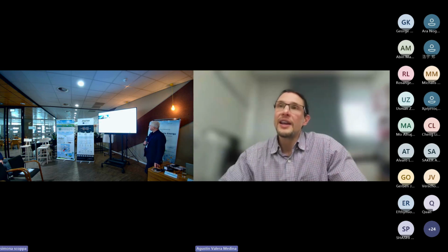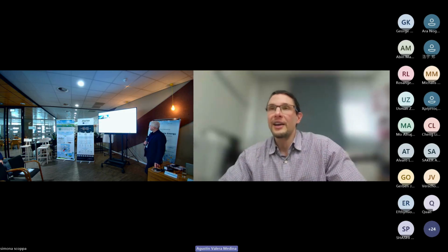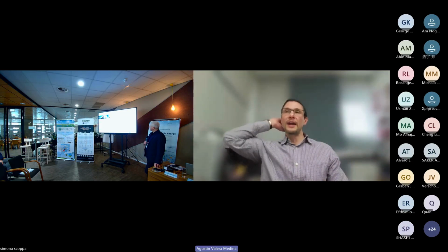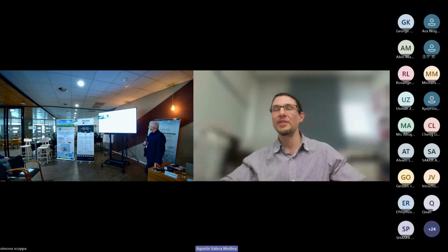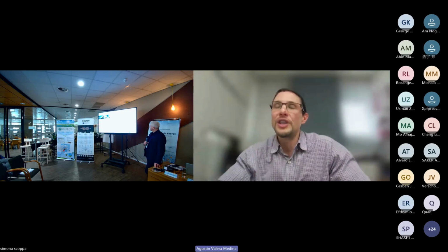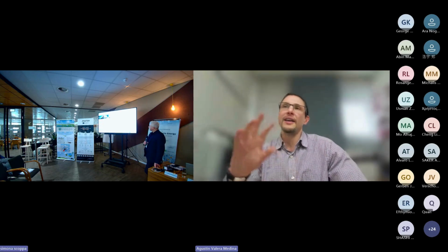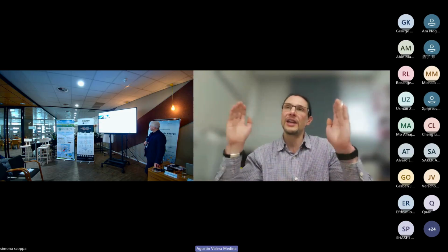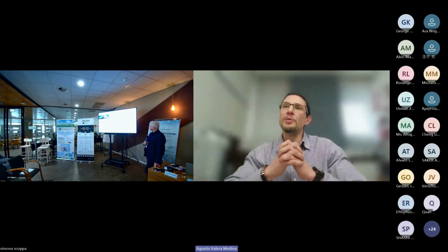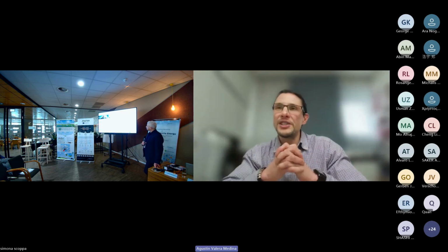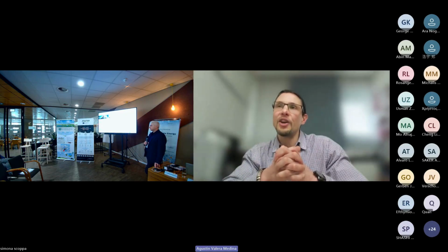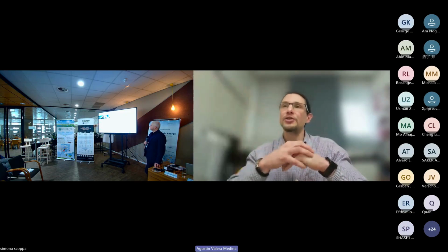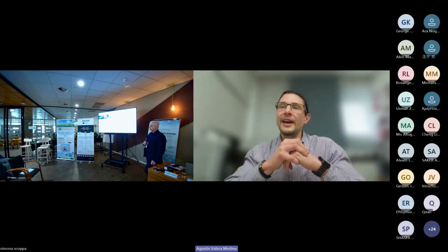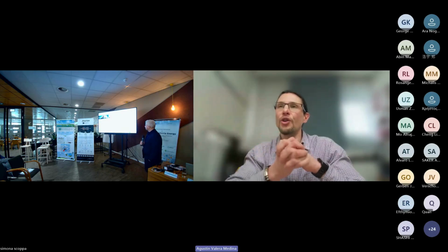It is a fascinating area, and actually, Boeing and NASA are working with the University of Central Florida on the concept. And all has been secrecy. They are going to present some results in Chile from the work that they have been doing. In our case, the way that we see it is using that plasma system to provide that feasibility. Ammonia is very dull, very difficult to burn, and compared to kerosene, that is one of the big issues. The amount of fuel you require for jet fuel compared to ammonia will give you around 45% of the flight potential that kerosene will give you. So thinking about 1,000 miles distance, ammonia will only get you around 450 miles.